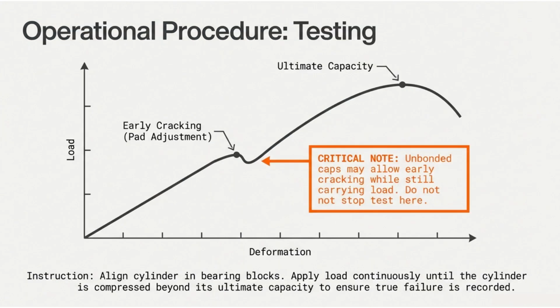Now we are at the actual test. Look at the load deformation curve. It shows an important point. With unbonded caps, you may see early cracking while the specimen is still carrying load. The slide gives a critical note. Do not stop the test here. In other words, if you hear a crack or see a small crack early, that does not mean the cylinder has reached peak load. The specimen can still climb to ultimate capacity.